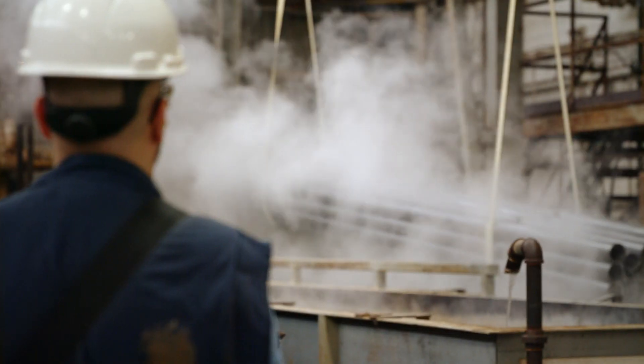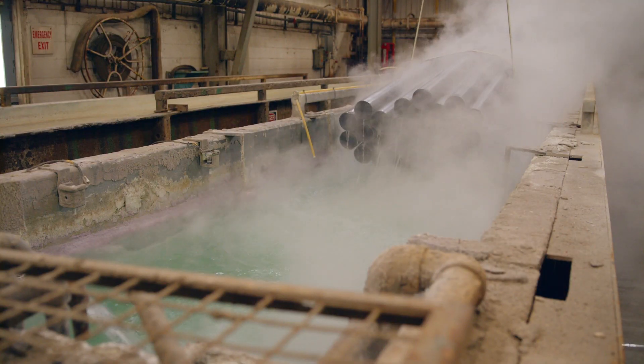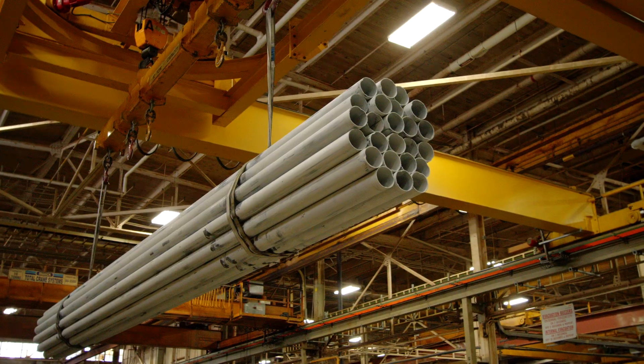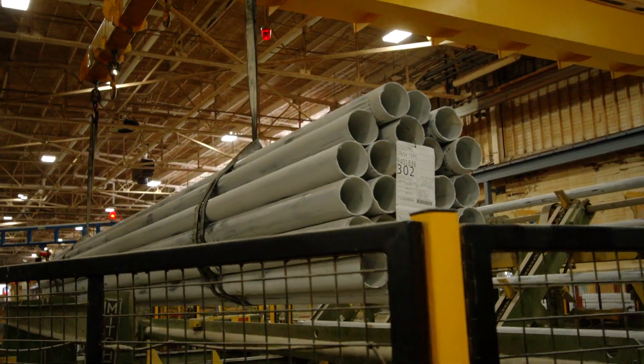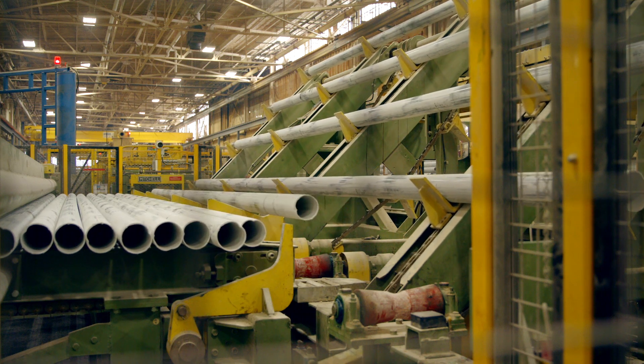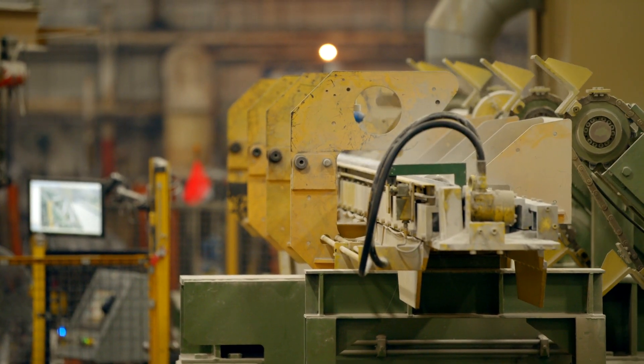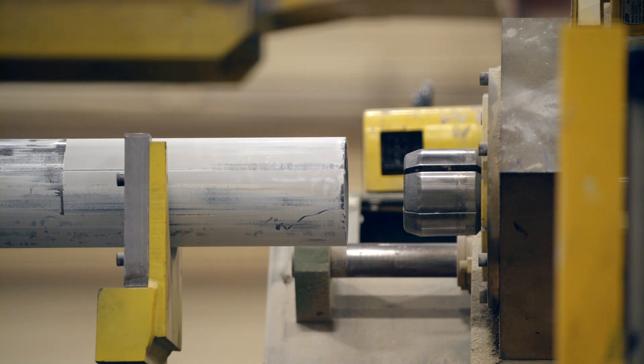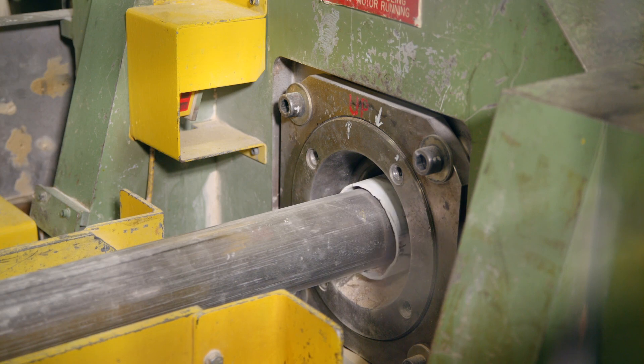After the mother tube is formed in long lengths, it undergoes further processing to make a Multi-Wall T3 tube component. A high-film strength dry lubricant is applied to prepare the tube for the cold-forming process. During cold-forming, the tube is longitudinally drawn through tools which reduce the cross-section, reshape the tube profile, and reduce the wall thickness. Tool manipulation during drawing creates a very accurate wall thickness profile according to the product requirements.